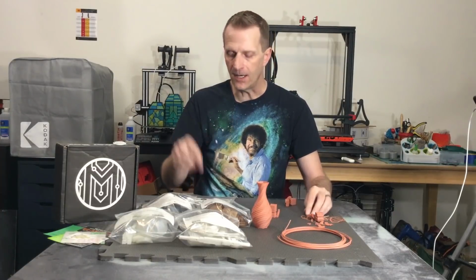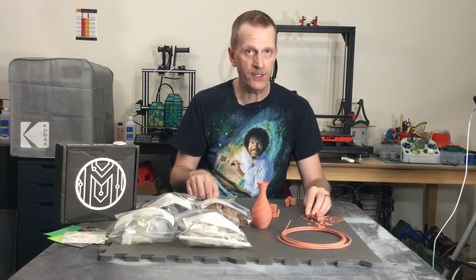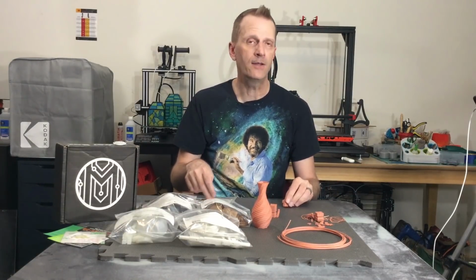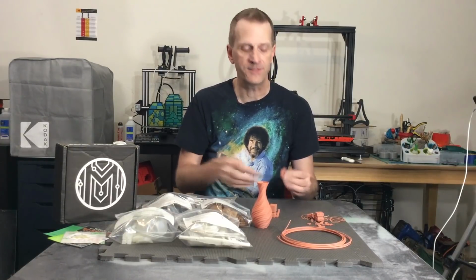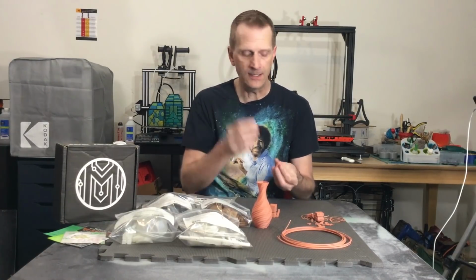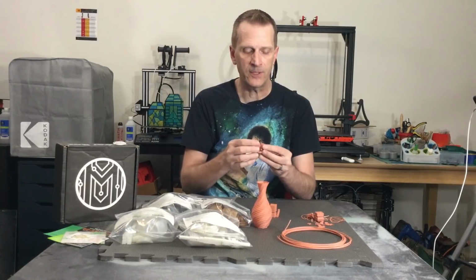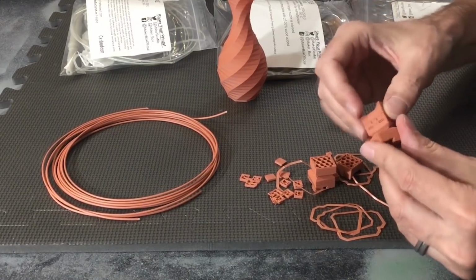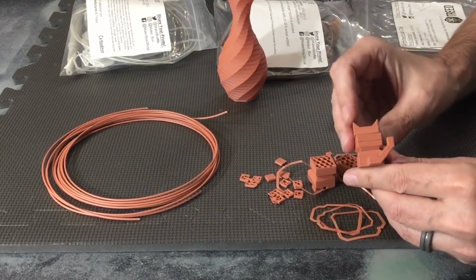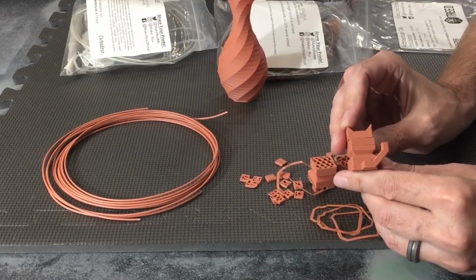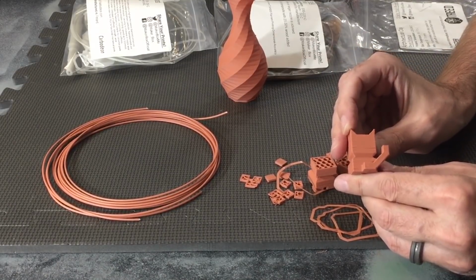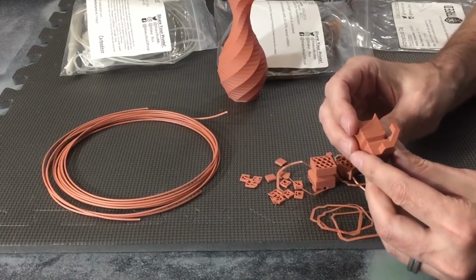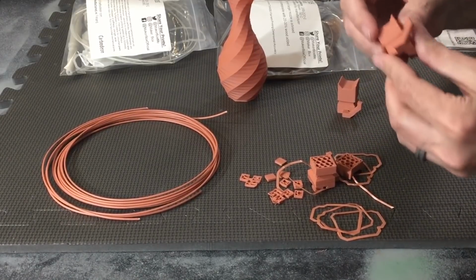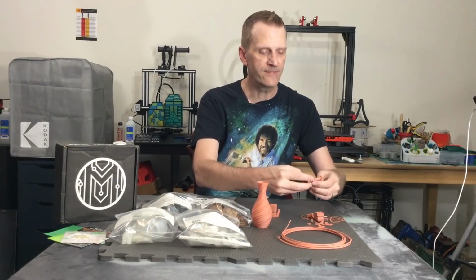So I amped up the heat on the hot end to 230 degrees C, and I increased the bed temperature up to 95 C. And on the next print, it did print successfully. It did stay on the print bed. But again, we had that, and it's hard to see, this one fell apart again in my hands. But we had the interlayer warping again, which again, I've never seen before. So when I pulled it off the print bed, it was intact. And then when I went to kind of play with it, it just started to fall apart. And it's very brittle.